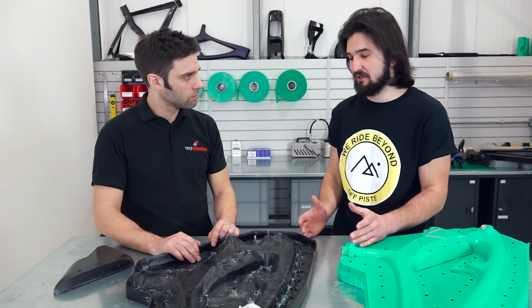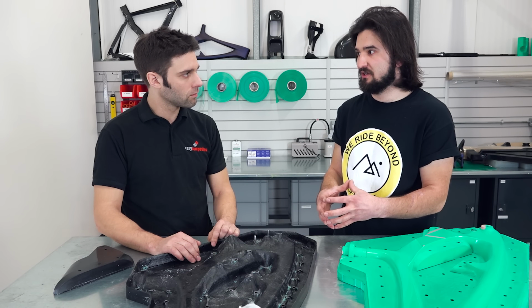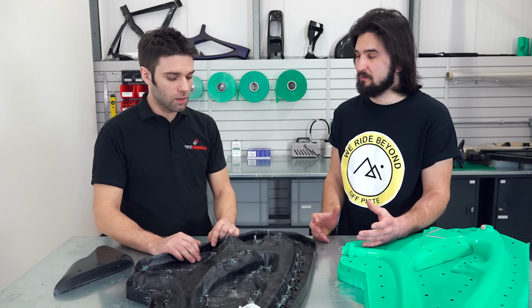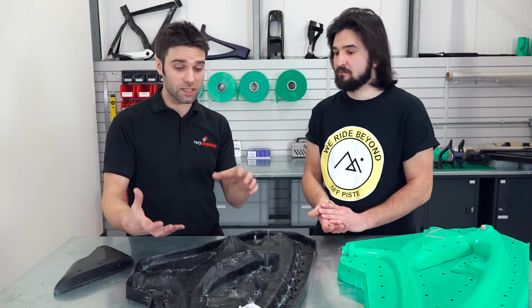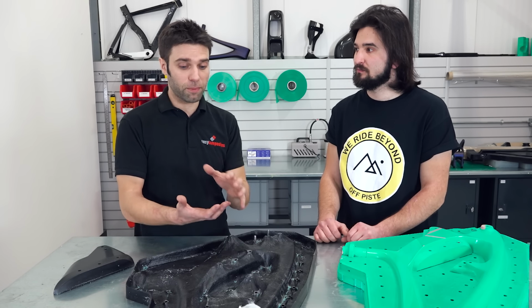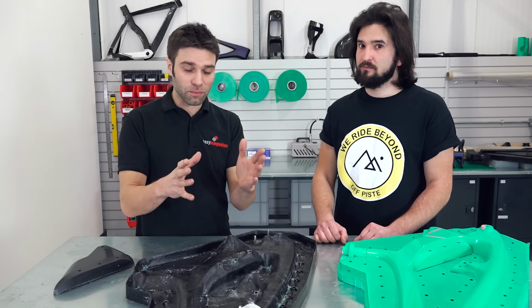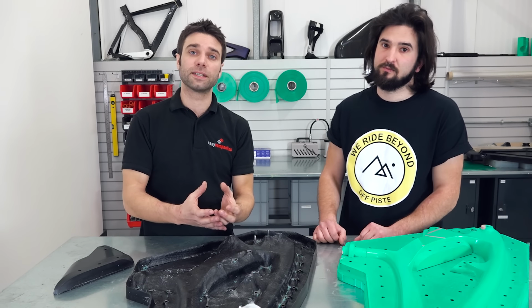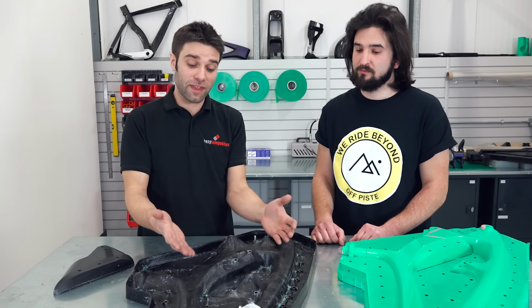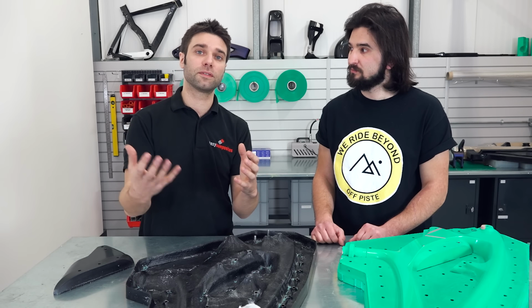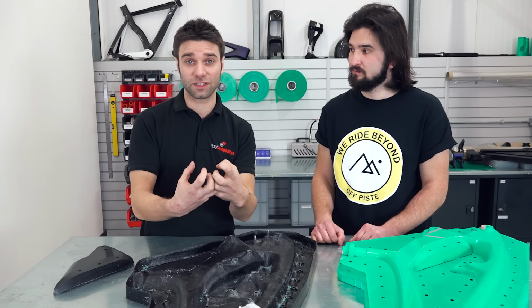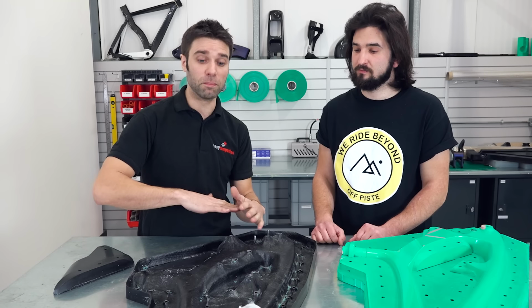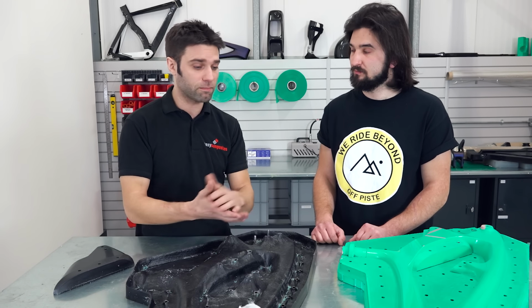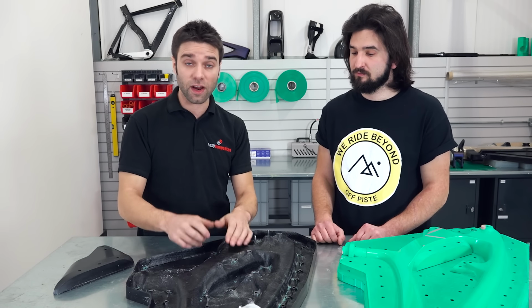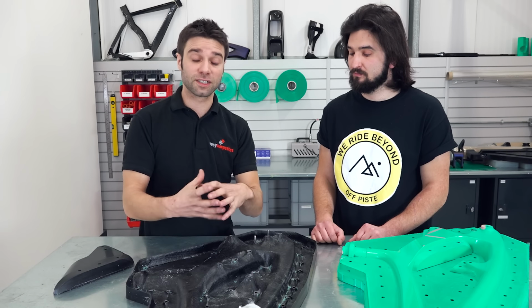But this was fixed by bolting up the two halves together. And post-curing them. So the final stage of the curing was actually done with the molds bolted together. When you do a post-cure, it slightly softens the resin, and if they're bolted together and pulled flat, when the resin softens and finally does its final cure and hardening, it will be much more accurate by putting the two together. So that's a great tip for anybody making pre-preg split tools.